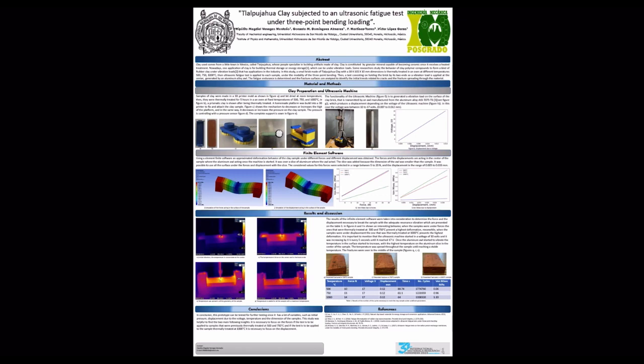Samples of clay were made with a 3D printer, molded as shown in figure A, and left to dry at room temperature. Then they were thermally treated for 5 hours in an oven at fixed temperatures of 500, 750, and 1000 Celsius degrees. In figure B, a prismatic clay sample is shown after being thermally treated. A homemade platform was built with a 3D printer to fix and attach the clay sample. Figure C shows the mechanism to decrease and increase the height of the platform, and in the same way it decreases or increases the pressure on the clay sample.